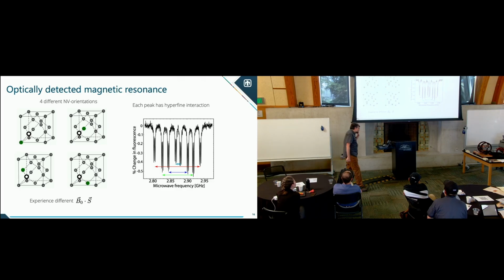But the nice thing about this is that it actually gives you vector magnetometry in this case. Not only are you looking at the splitting of the outer peaks, but since we know the different orientations, you can actually reconstruct what the vector field is if you can do this magnetic resonance. Okay, so that is the overview of the physics of the nitrogen vacancy.